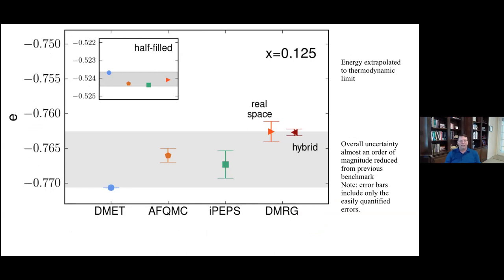So in the end, we ended up with very close agreement in terms of the energies for these four different methods, including two versions of DMRG. The smaller errors came from the hybrid real space momentum space. Now they all have error bars, and you shouldn't think that there's something significant about the error bars not overlapping, because there are some error bars that are easy to quantify, like statistical error, but one has no idea how to quantify the constraint error in the quantum Monte Carlo. So these only show the easy errors, and without this comparison, you don't really know what the uncontrolled errors are doing. In this case, it's primarily extrapolation for the DMRG from a small cylinder to a wide cylinder.